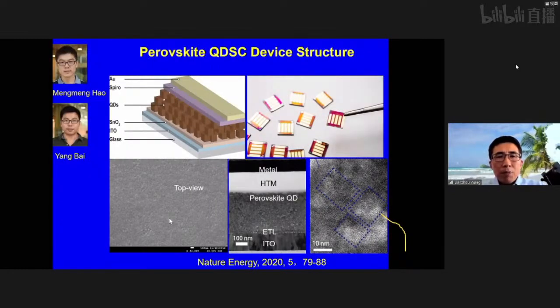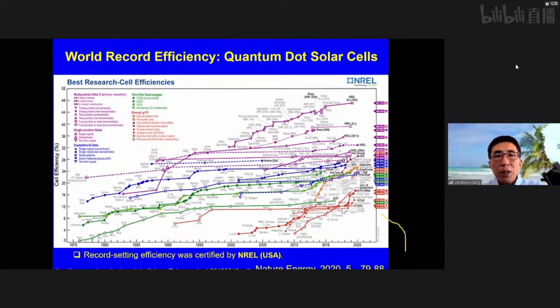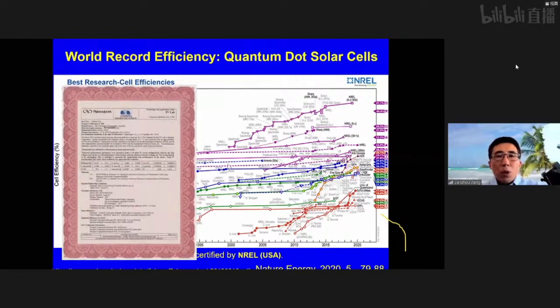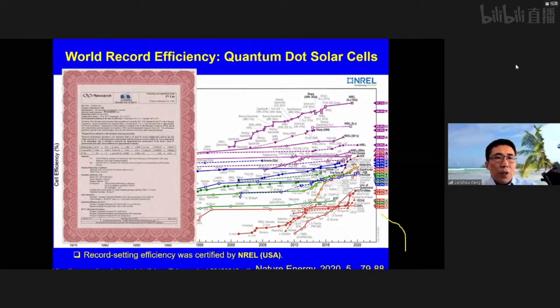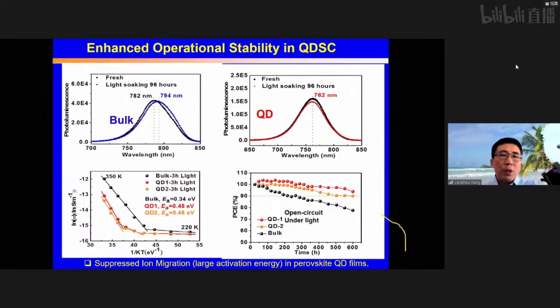By using this, we can prepare some devices, because the quantum dot solar cell has a very good efficiency and is certified, and it's been recognized in this efficiency chart. In this one, what we really want to show is the stability of the materials. As I said, these quantum dots have some ligands on the surface, which can provide a good way to protect the quantum dot from phase segregation. Compared with the bulk phase, we can see the quantum dots upon light soaking for 4 days don't show any difference.